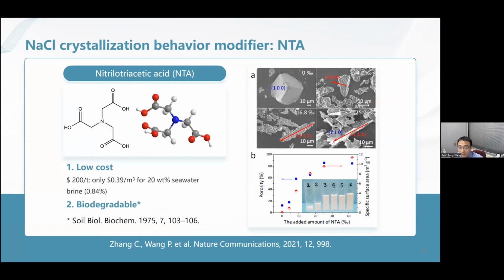I would say that we were really lucky to find a chemical called NTA, not very expensive, it's even biodegradable. So we took this chemical and added just a little bit into, in this case, the pure sodium chloride solution. We want to see whether this chemical can enhance the porosity of the sodium chloride crystals during the evaporation crystallization process.